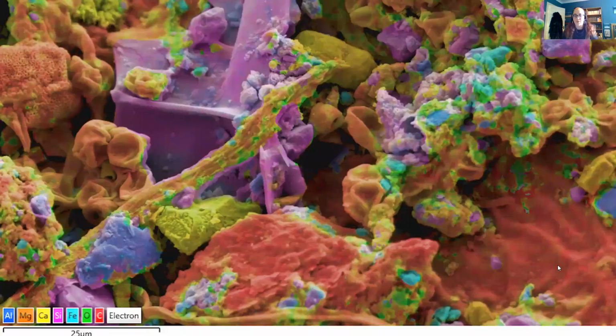And this is a micrograph I collected as part of a collaboration with Rob Kessler, looking at air particle pollution on the surface of leaves. And these are all various different particles that have accumulated on the surface. And this is an electron micrograph where we've applied colour, and you can see down here the elements, and the signals from each of these elements are coloured differently, and you can see this blend of information. And that's really helpful to interpret visually what is going on in our sample.